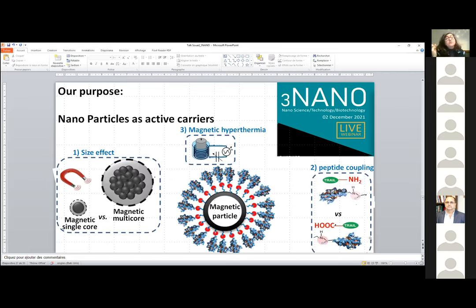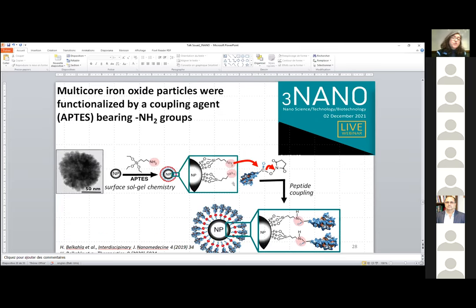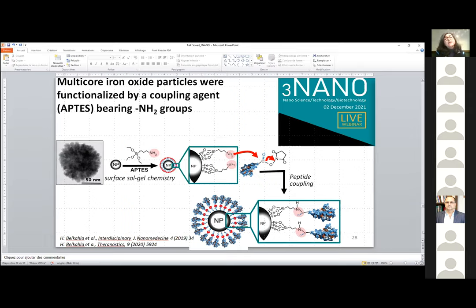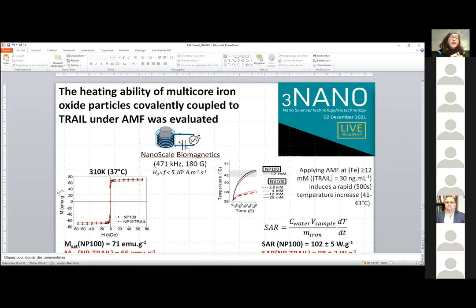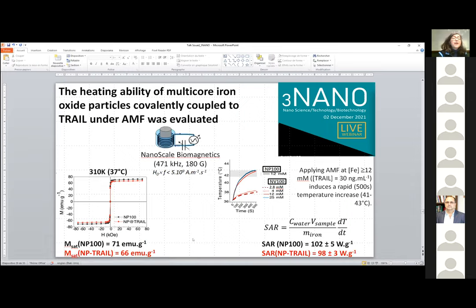And then we decided to apply an alternating magnetic field and to see if we have any effect of this alternating magnetic field when TRAIL is present. So for that, we focused on the largest particles in size because they exhibit the highest magnetization. And you know that for effective magnetic heating, we need a high magnetization. And we attached TRAIL to these particles using the same strategy, I mean, sol-gel chemistry through the APTES reagent. Okay, so you know that by this coupling process, we have about 10,000 protein molecules at the surface of each particle. I plotted here the magnetization as a function of the magnetic field of our bare nanoparticles and the nano hybrids at 37 degrees C.